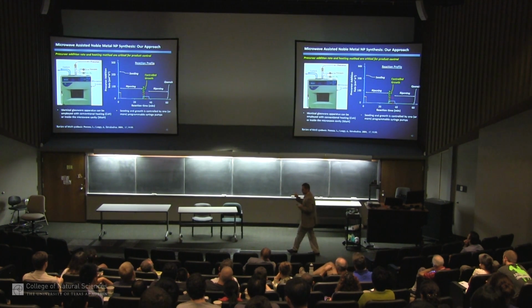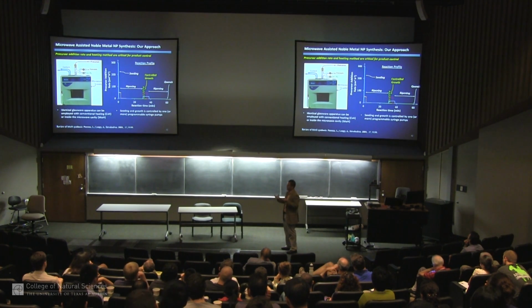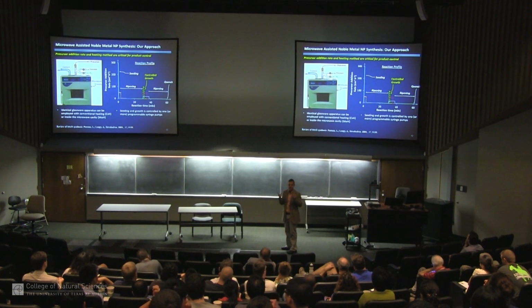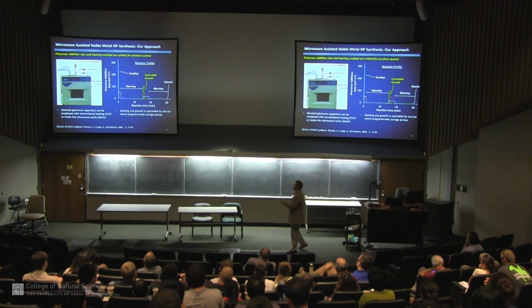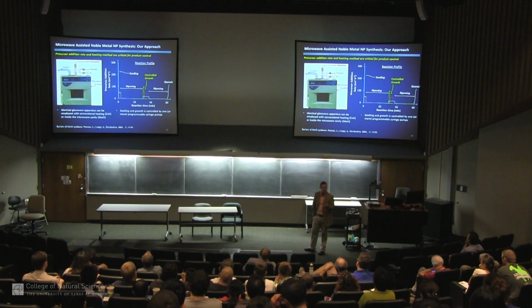In this case, if we use polar solvents and the reagents themselves, the atomic species are very polar, they couple to the microwave heating and they dissipate heat very rapidly in small spots, and these are called by the microwave chemists hotspots. And these hotspots can be several hundred degrees hotter than the bulk temperature. So the bulk temperature may read 150 degrees on a thermometer, but you've got areas in the solution which are short-lived, but could be several hundred degrees hotter, and they're really nice nucleation sites for making nanoparticles.